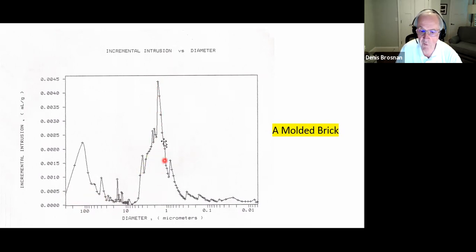But if we kept on firing this brick, this peak would lower in intensity, and this peak might also lower in intensity. So we'll tend to coarsen pores. So we'd have some other peaks show up in this area. Some of these peaks would get larger in intensity during the firing process.